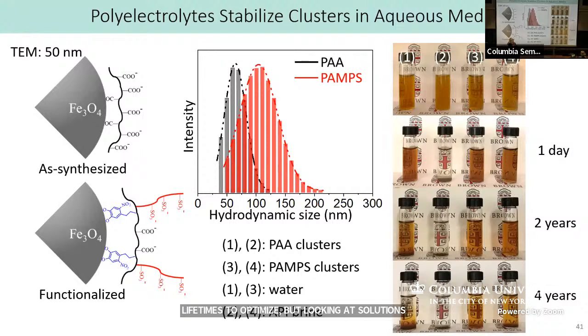What that means is colloidal stability: the fact that these solutions, especially the one on the far right here, still look clear and brown means the particles are not aggregating together. Even in the presence of a field, they won't. The particles are little aggregates, but in solution, they're like non-interacting particles. We achieve that by putting pretty high charge densities on the particle. We use a polysulfonate system that is actually approved for use in humans or close to it. So we think that's not a problem, but we're able to manipulate stability of the particles.